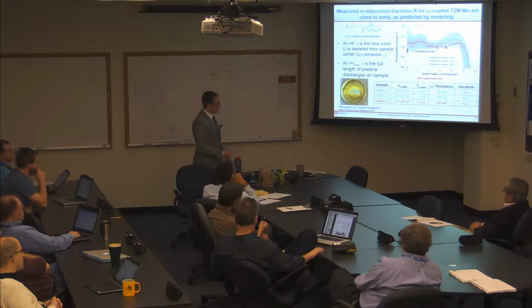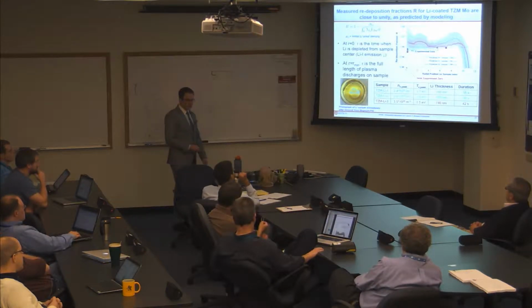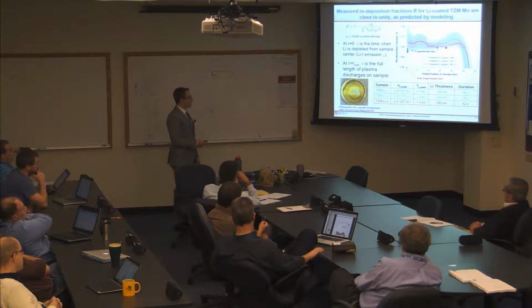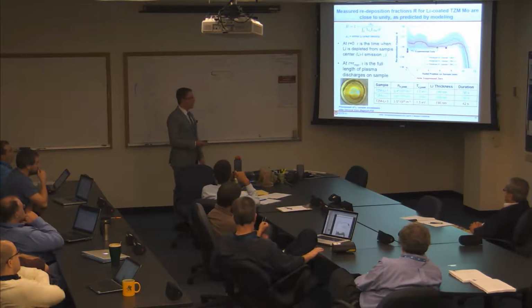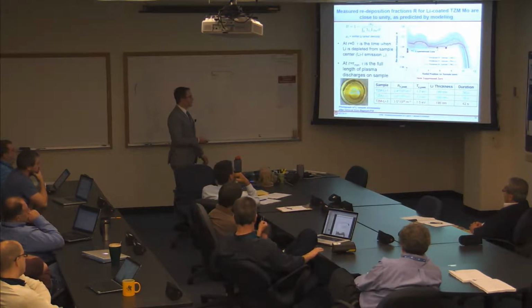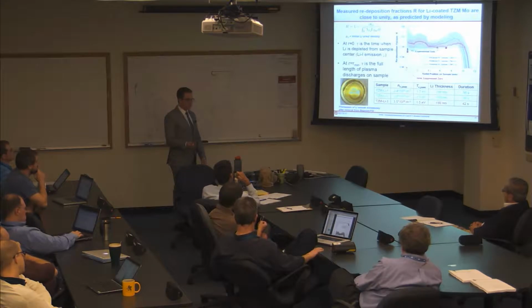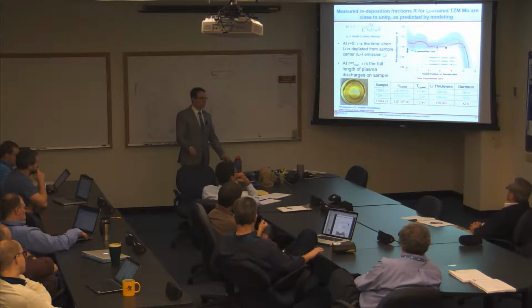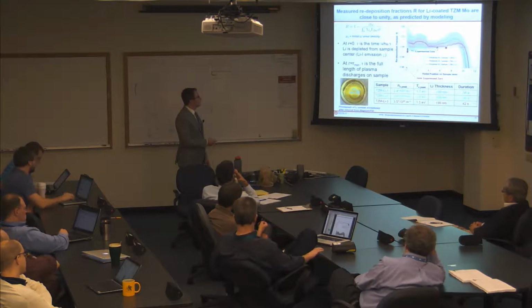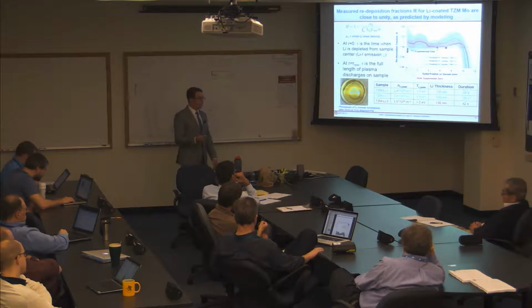Okay, so how do the experiments compare with the data? So first of all, how do I measure redeposition fraction? Well, as I mentioned earlier, you start to see the lithium erode, or deplete rather, from the center of the sample after only about 1 to 2 seconds. So you can calculate at that depletion time, which I call tau, what is the total lithium fluence that has actually come off of the target. So that's this quantity in the denominator here. And then you compare that with the initial areal density of the lithium film, which I call rho.